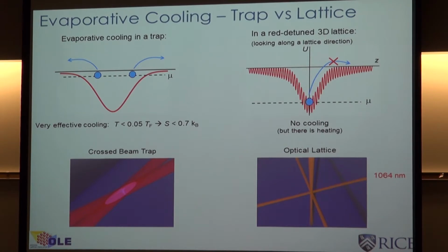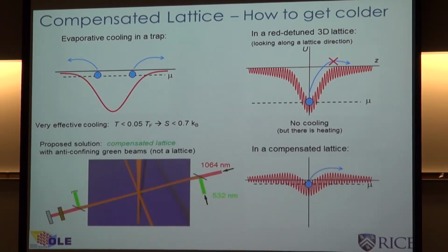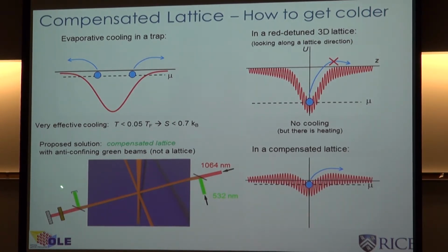Now what we decided to do was to compensate this harmonic confinement by applying an additional blue detuned laser beam. This green beam here is not retroreflected, so it doesn't produce a lattice itself. Its only purpose is to superimpose a positive envelope that compensates this attractive envelope of the lattice. And so the result is something like this. You have a knob now of where you set that chemical potential to this evaporation threshold, and that knob is the intensity of this green light. That's the entire concept of this compensated lattice: it facilitates atoms at the edges of the trap to leave and thereby get colder.